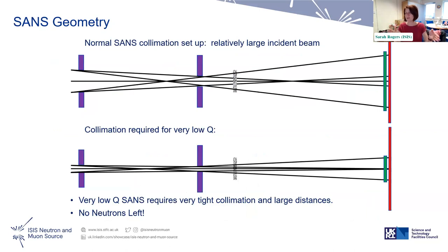So that's the first distance. And we try and match L1 to L2, where L2 is the distance from the sample to the detector, to get the optimum resolution. Now, what happens is that obviously a lot of the beam barrels straight through the sample and doesn't scatter. So on the detectors, we have to have something called a beam stop, which is this green thing here. It's roughly the size of the beam that comes out of the sample that's not small angle scattered, so to speak.